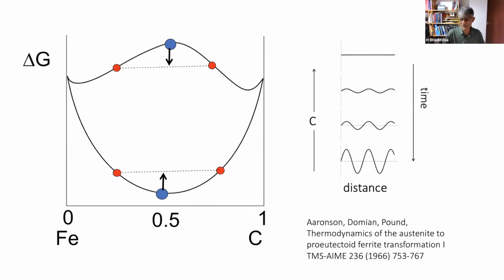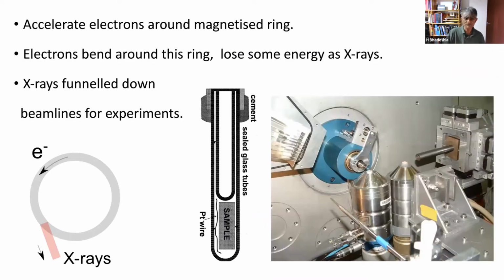And one way you can do this is using diffraction. So we have a sample of steel, which is about 5 millimeters in thickness, inside this inert atmosphere, and there's an annealed platinum wire for reference, and the whole thing is sealed. We then put it into a holder, and this is a synchrotron beam line for powerful X-rays, and these are heaters with which we can austenitize and then cool in a controlled way to the bainite transformation temperature.